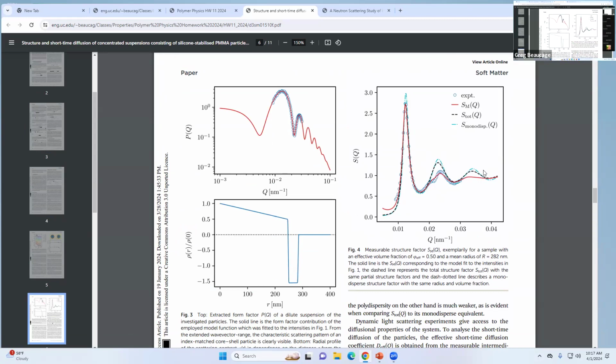Then you get to the second order and third order. So this is more or less like the correlations. You have spheres coming up, and then there's going to be like a correlation hole because they can't pass through each other. So that's going to be like the radius. So you kind of have the radius of the sphere here or here, because it can't get into the other sphere. That's excluded volume. Then because of that, the things that would have been in the other sphere pile up at the surface. They were randomly distributed, but then you say they can't be here, so they have to move. So they move over to be around it. So that's the first order shell.